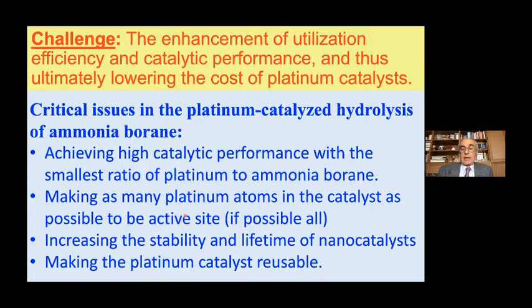So in a solid catalyst, only the surface atoms are active. The atoms in core are not. So that means we have to try to keep the surface atoms as high as possible and no inactive core atoms, if possible. Increasing the stability and lifetime of nanocatalyst, in that case, platinum nanocatalyst, and making the platinum catalyst reusable. That's also important. We should not use just once. The platinum nanoparticles or catalysts, we should be able to reuse them.